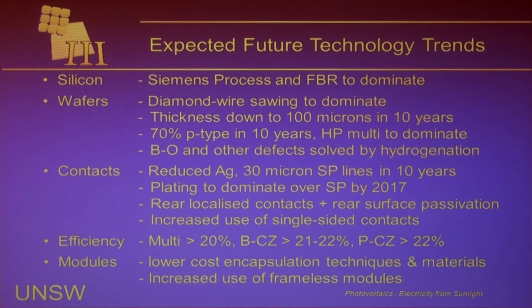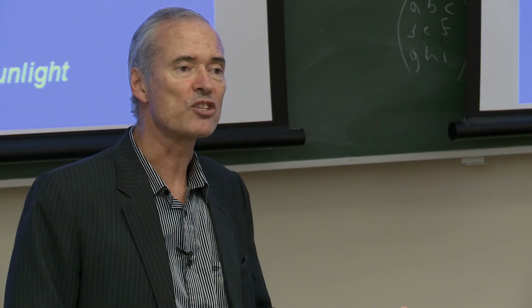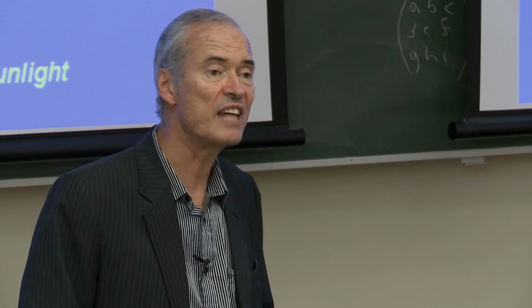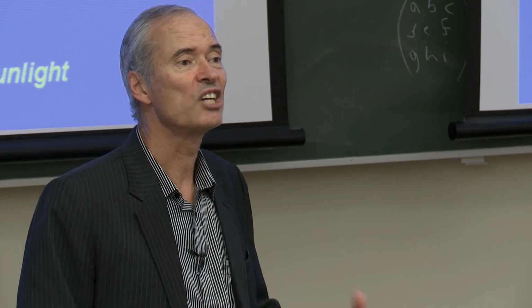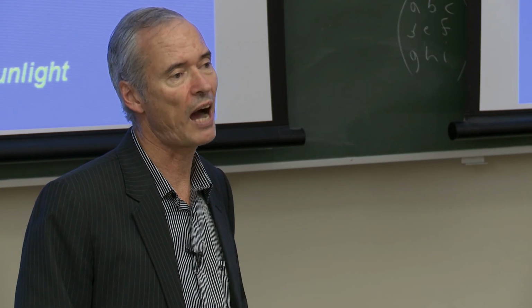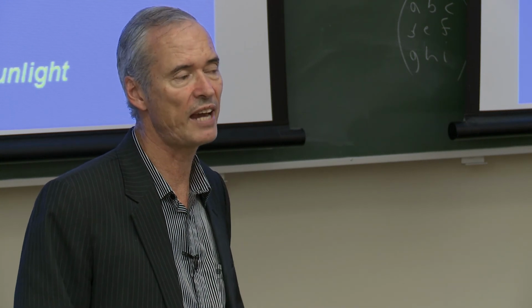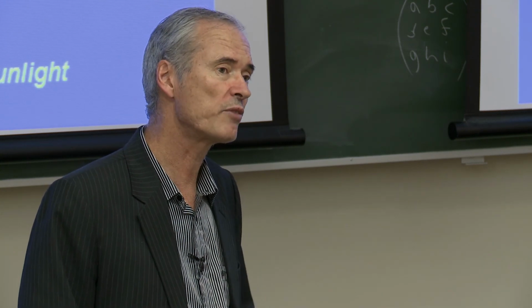Okay, then we get to the metal contacts, a very important part of making a solar cell. You need to extract the current from the solar cell. You need metal on the front and back with a conventional design. And looks like my laser pointer's dying. But anyway, at the moment, silver is predominantly used for the top metal contact. The trouble is, with the growth in photovoltaics, the industry is now using so much silver that it's contributing to pushing the price of silver up, aggravating the shortage of silver internationally. And so the price of silver has gone up very significantly.